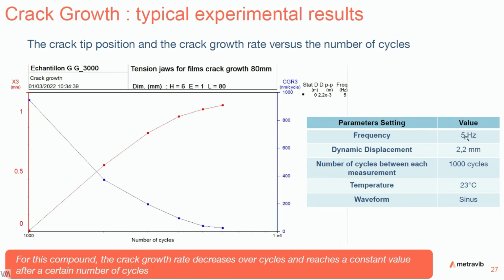Frequency was 5 Hertz, dynamic displacement was 2.2 millimeters peak to peak. The number of cycles between each measurement point was 1000 cycles, at room temperature, and we use a sinus waveform. It's simple and really typical for this compound. The crack growth rate decreases with the number of cycles, and of course the length increases.